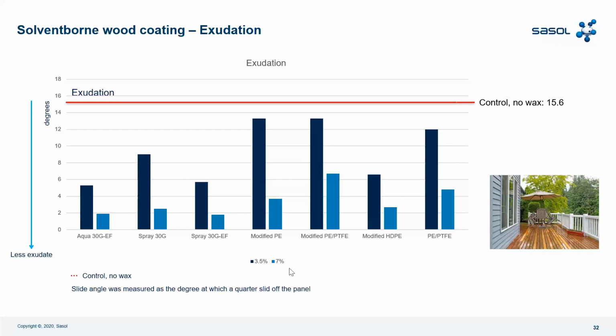This, I think, is very important for you, because exudation is a problem in wood coating, and our Sasol Wax Aqua 30 GEF, the modified wax, achieved a very good result. Not only this product, but also our Spray 30 GEF achieved good results if you don't want to use a modified Fischer-Tropsch wax, and follow with Spray 30G, not the extra fine. We can continue, so best are Aqua 30 GEF and Spray 30 GEF.